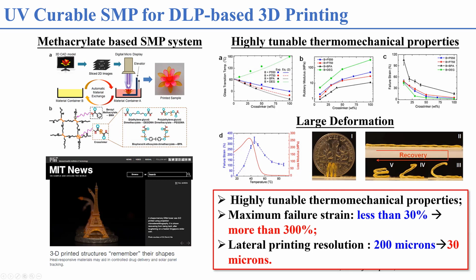This material is highly tunable in its mechanical properties, and it exhibits large deformation, deforming by more than 300%. Also, because this material is compatible with DLP-based 3D printing, we can print at very high resolution. For example, the highest resolution achieved is 30 microns. But this material is methacrylate based, and the methacrylate functional group makes the chemical reaction quite slow.